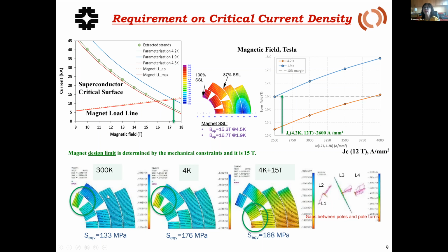However, when they design the magnet, there are three fundamental stages of design. The room temperature stage, when you have assembled your magnet, you have pre-compressed it in its mechanical structure, and it sees a certain distribution of strain, which I'm showing here. Then you cool it down to 4 Kelvin, and the differential thermal contractions come into effect and completely change the stress distribution in the coils. And then when you throw the current in there, your 15,000 amps or whatever it is, again it completely changes the stress distribution in this third stage because of the Lorentz forces. So it's very complex. Anyway, they come to you with a given minimum critical current density that the superconductor has to provide.